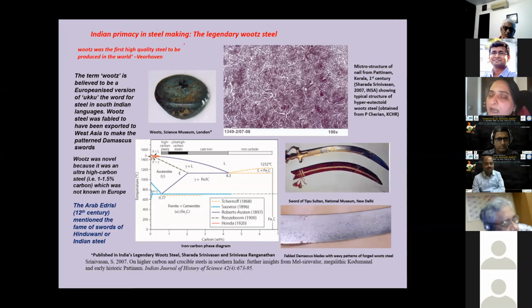And so I had undertaken this microstructural analysis of a nail from Pattanam in Kerala from the 1st century. And this is really the structure of typical hypereutectoid Wootz steel, which is this 1.5% carbon steel, where what has happened is that it has been heated to such a high temperature that there's a sort of molten carburization where it has gone into the austenite phase. So it is at least plastic, if not entirely molten, and that's how so much carbon could get into it.